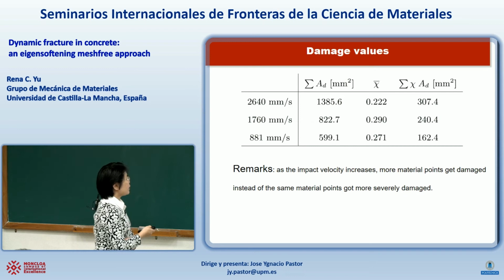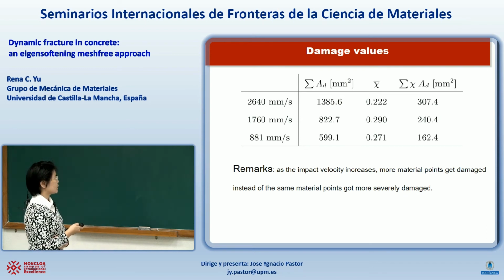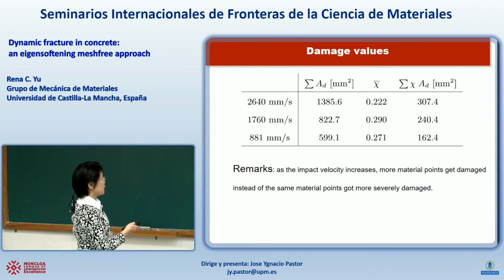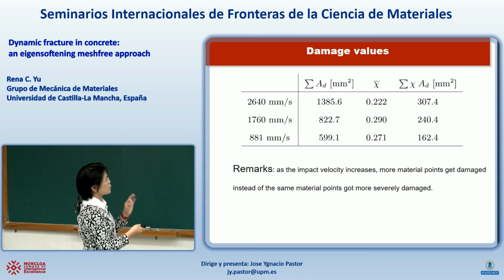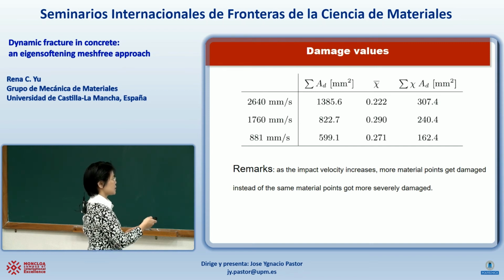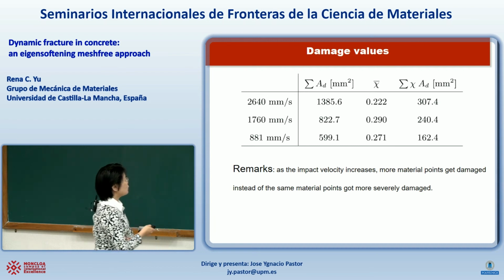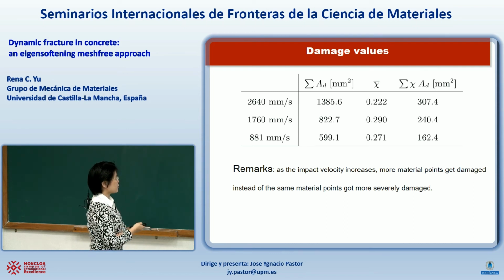And quantitatively, this is the area of damage for those 3 velocities. If we multiply the corresponding material point area and the damage value, and we sum these terms up and divide by the total area, this is the average damage for each velocity. We see that those numbers are not really significantly different. As the impact velocity increases, more material gets damaged, but the same material does not get more severely damaged.